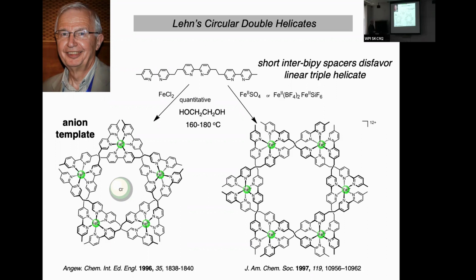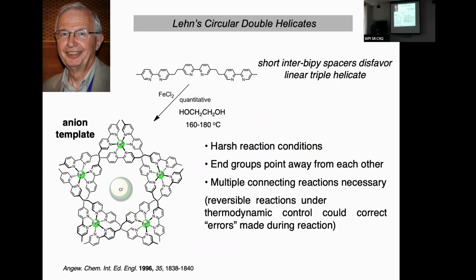a more complicated link. However, it's a little bit more difficult to do that than it sounds, because if you note here, the conditions are very harsh. You have to heat this at 160 degrees in ethylene glycol because the coordination of iron chemistry is so slow. And then also, although this looks nice in the ChemDraw structure on the slide, actually these end groups point directly away from each other. And so being able to connect them round together would be very entropically difficult. You would cost a lot of degrees of freedom of the chain to fold round to do that.